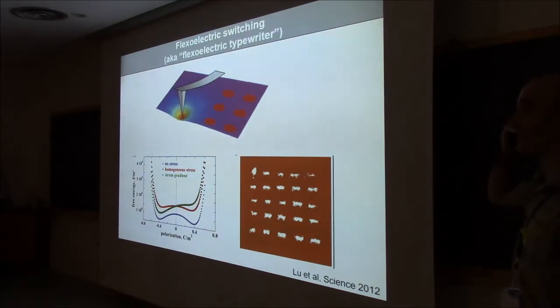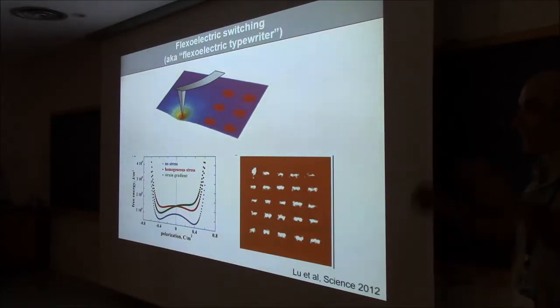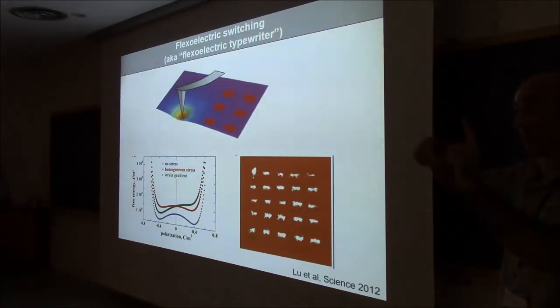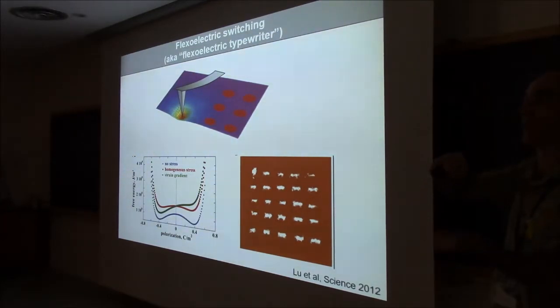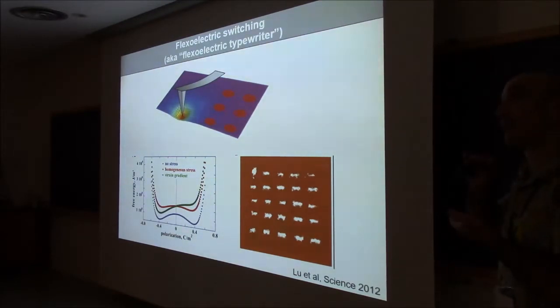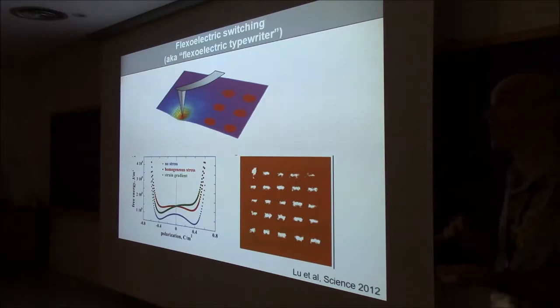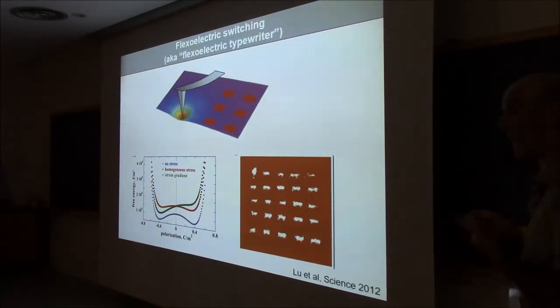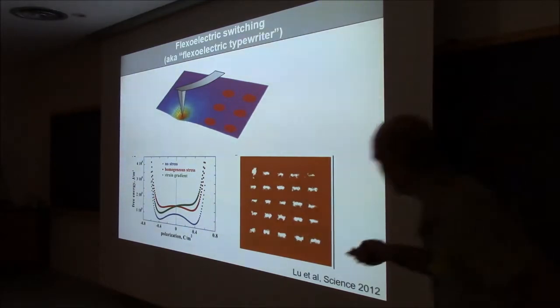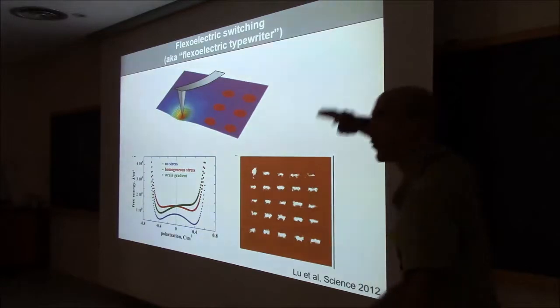Now remember what I said at the very beginning of my talk, the shape and size of the unit cell for the up state and for the down state are identical. So if I apply homogeneous pressure to a ferroelectric, I will never be able to switch it by pure pressure. But if instead of pressure I apply a pressure gradient, a strain gradient, now I can switch the polarization. And this is exemplified here with the free energy. This is the free energy of bulk BTO. This is the free energy of BTO with homogeneous compression. It's still symmetric, so there's no reason to switch from one side to the other.